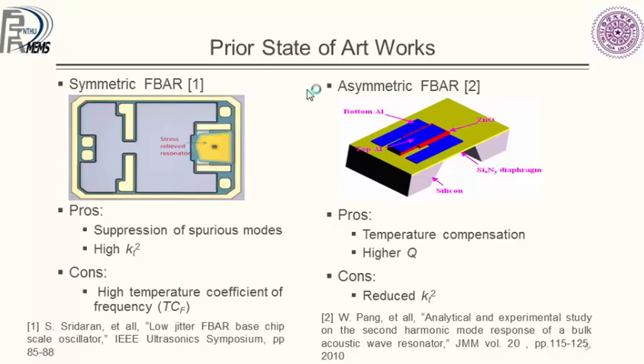The second design is an asymmetric design that uses an additional silicon nitride layer. This additional layer can be used for temperature compensation or to enhance mechanical properties such as higher Q. The drawback is a reduction in the coupling coefficient kT-squared, because the response is now dominated by the additional layer as well.